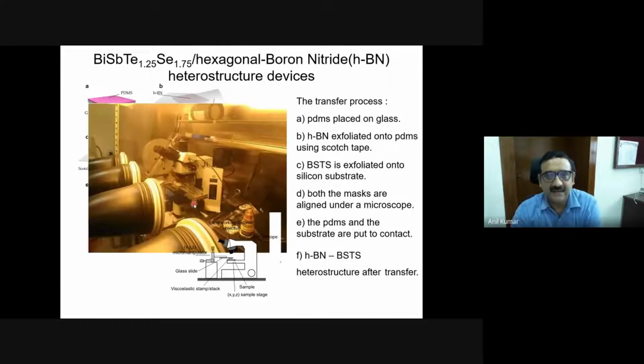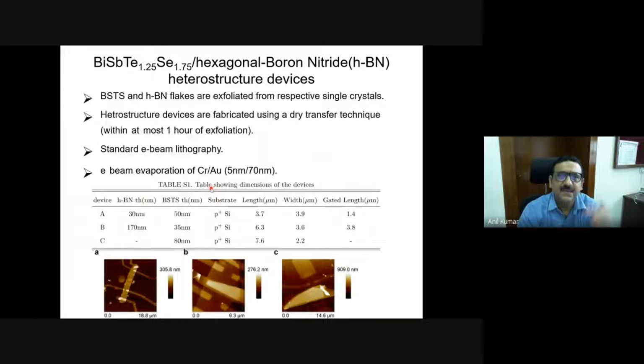And this is all done in a glove box, because moisture and oxygen should not be there. We have fabricated the stages in a microscope that is kept inside the glove box. So the crystal is exfoliated inside the glove box, and then we make this transfer and cover it with HBN, and we take it out for the lithography. We make several such devices, and each device looks different in shape and size. The reason is that this is done by exfoliation; if you put a Scotch tape and remove it, it just gets into an arbitrary shape.